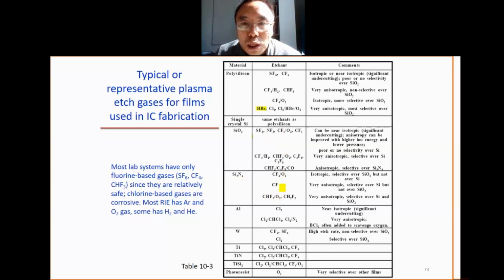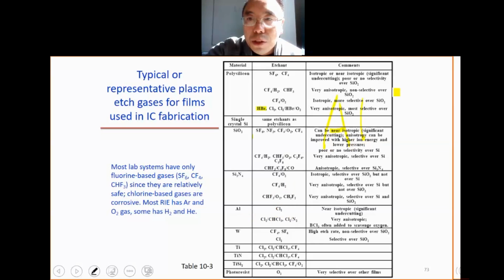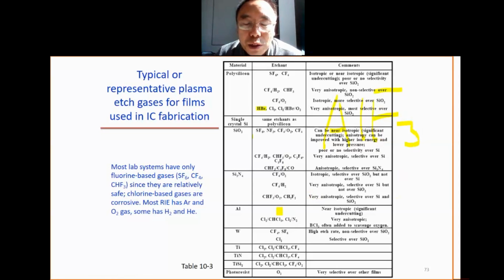Silicon nitride also uses different kinds of fluorine gases. For aluminum, we need to use chlorine gas because aluminum fluoride is not volatile, so the fluorine gas will not etch the aluminum, but chlorine gas can do it. For tungsten, we can use fluorine gas and chlorine gas. Titanium, chlorine, fluorine. Titanium nitride, titanium silicide. Photoresist, we can use oxygen to etch. Actually, if we use fluorine gas, it can also etch the photoresist. But when you use fluorine gas, the etching selectivity between the resist and the silicon will be low. But when you use oxygen, the selectivity can be very high. So you etch the resist without etching away the silicon below.